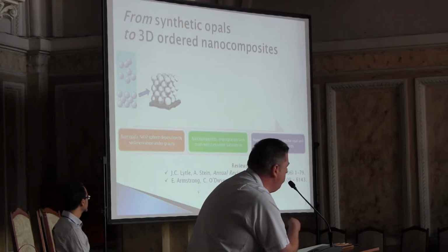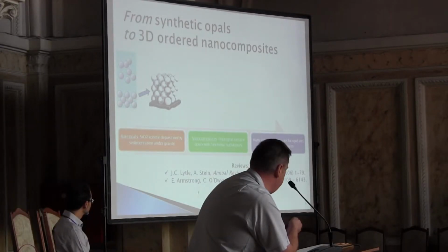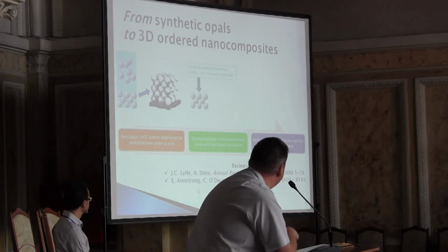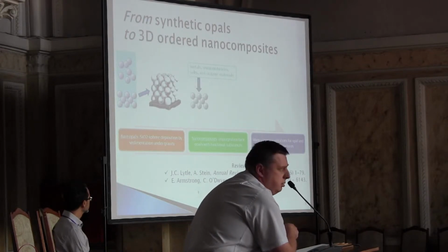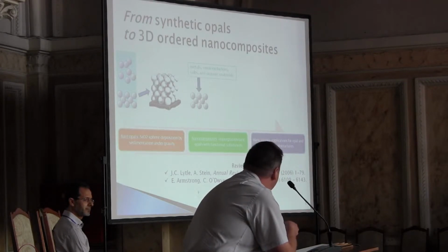The globules or spheres were prepared by standard Stöber methods, and then after sedimentation under gravity forces, we obtained such a regular structure which forms a face-centered cubic lattice.